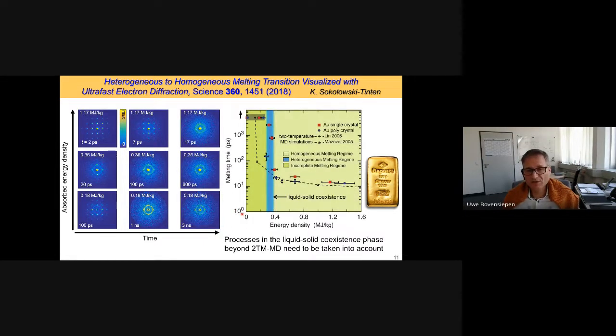So they looked in their analysis at the dependence of this melting time as a function of the energy density. And in this high energy density regime, you see here that these melting times agree very well with these dashed lines. And these are molecular dynamics simulations that are based on the two-temperature model. But if you go to this intermediate energy density, then you see that the experiment deviates from the simulations. And this has to do with the liquid-solid coexistence that they have observed here. And they basically conclude that for a good understanding, these models have to also take these coexistence problems into account.